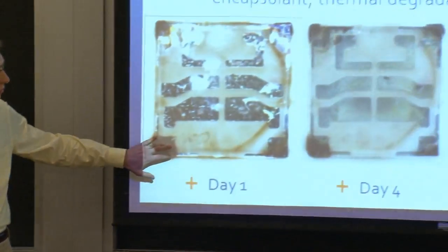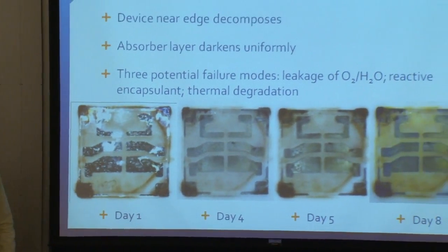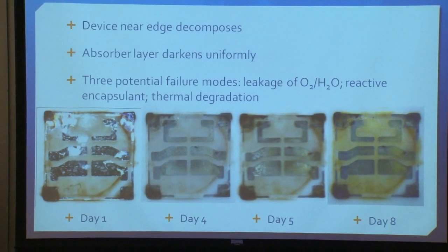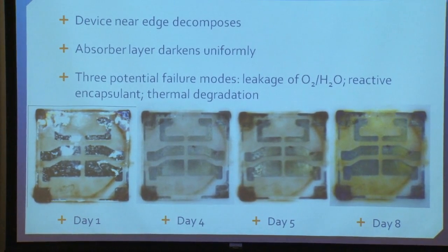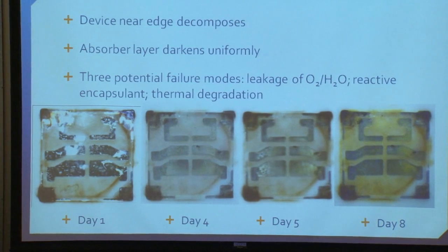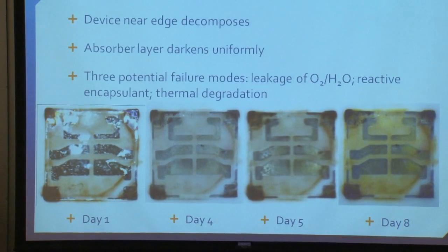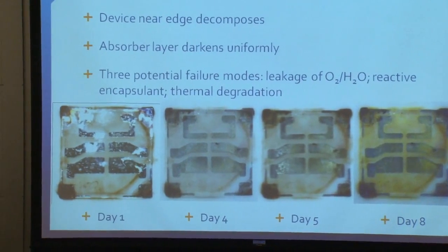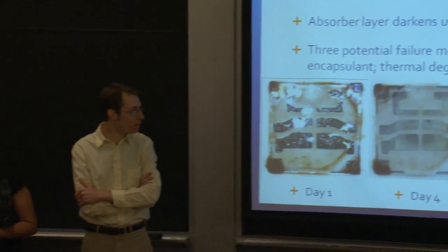For the quantum dots, it's a little bit less clear if there's a reaction with the EVA or not, because there's both degradation, or color changes, from the outside that affect particularly the outside, and there's also color changes that affect the whole device. And so then it's either the quantum dots are somehow changing, or there may be some kind of reaction with the encapsulant. But when we took the SEM images, the EDX aspect of it was not working, so it was difficult to do any kind of elemental analysis there.